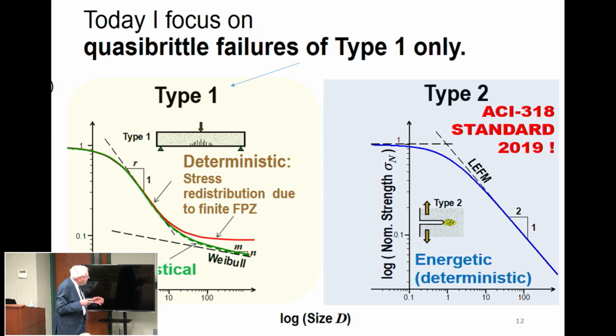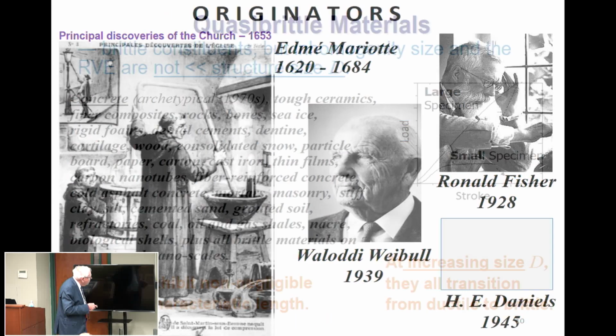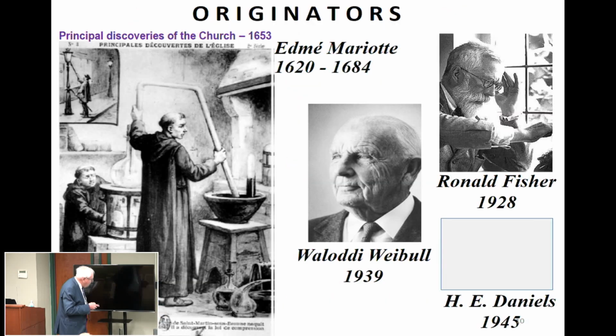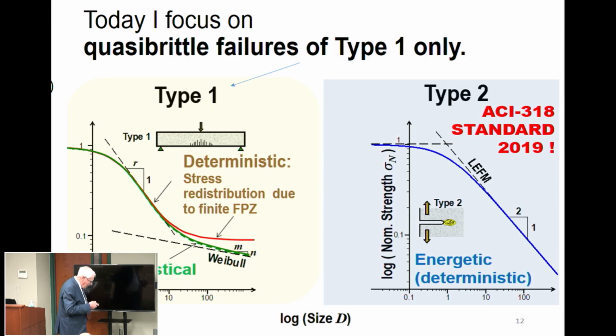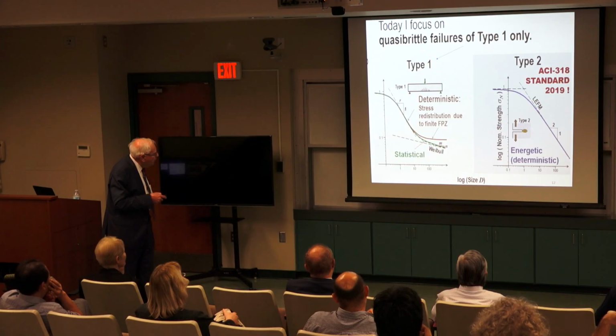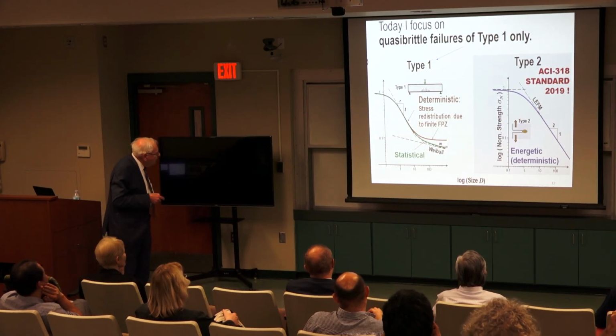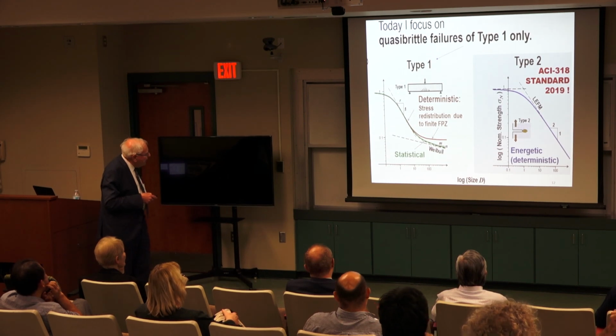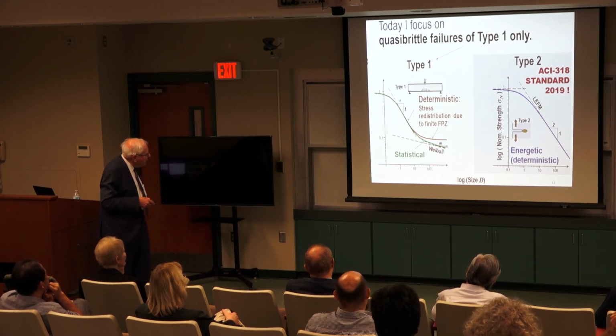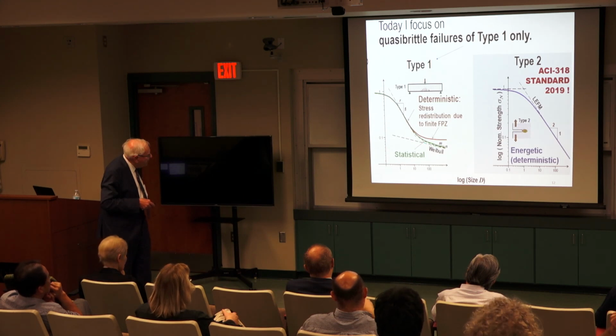The specimen becomes unstable as soon as you form the full fracture process zone and the macro crack starts to propagate. So this is still the damage zone or fracture process zone, and the crack starts going from here, and that's the moment of failure. So it can be considered deterministically, and behavior is like this. If you add statistics, you find out eventually it goes to Weibull statistics exactly.